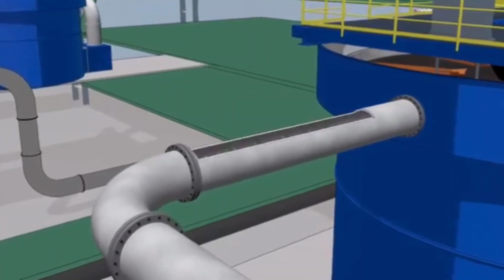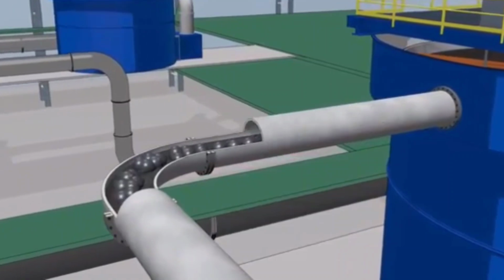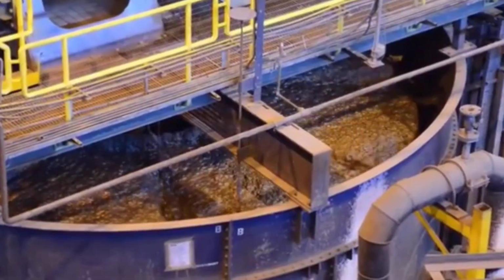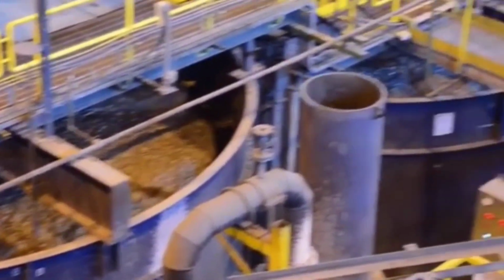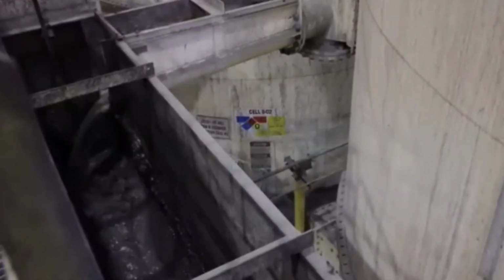A rotating mechanical arm gently skims the froth from the surface, guiding it into a concentrated stream of copper concentrate. Each tank can handle up to 1,000 cubic meters of slurry per hour, the equivalent of nearly 20 family-sized swimming pools in constant motion. The entire system runs automatically, and even small shifts in airflow, chemical balance, or temperature can significantly affect how efficiently the copper is recovered.